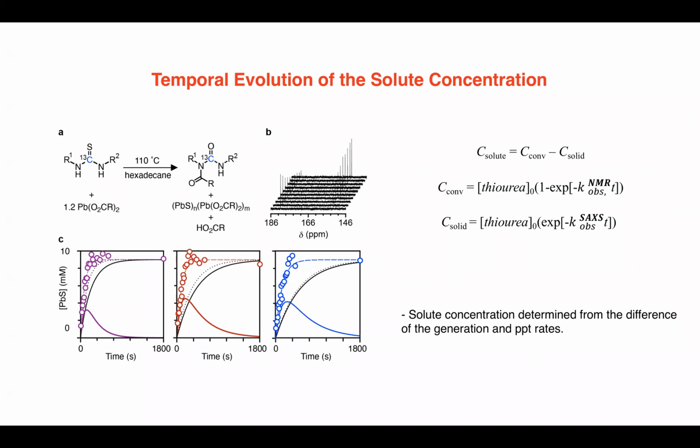So in these reactions, we have slow nucleation. The solute concentrations reach very high levels. So this is all lead sulfide. In the other reaction here, you can see the solute, about a third to a half of all of the lead sulfide, is not in particles and not in precursors in one of these reactions. And it's very LaMer-like in the sense that the solute concentration goes up and then it decays as it approaches equilibrium. What's not LaMer-like is the nucleation phase being short.